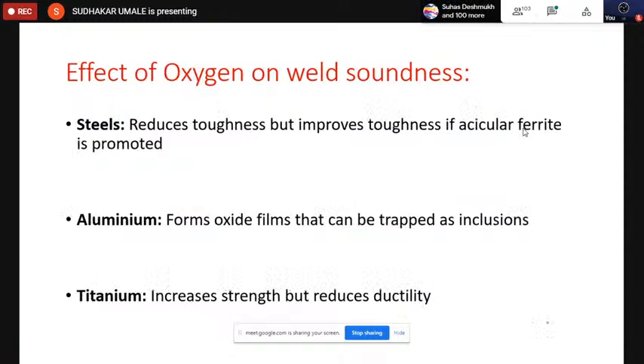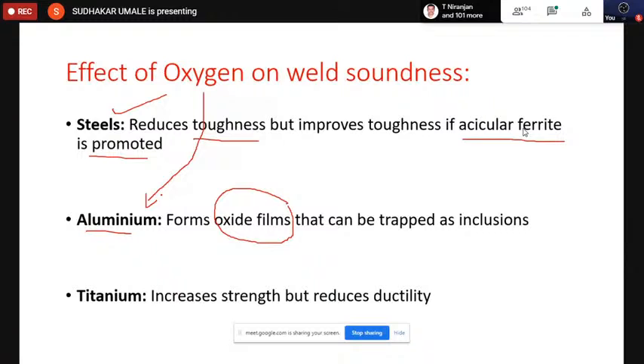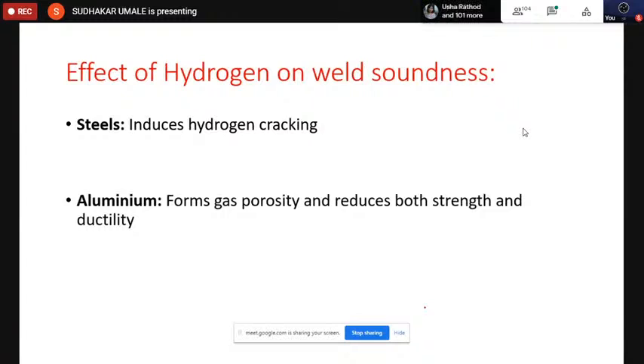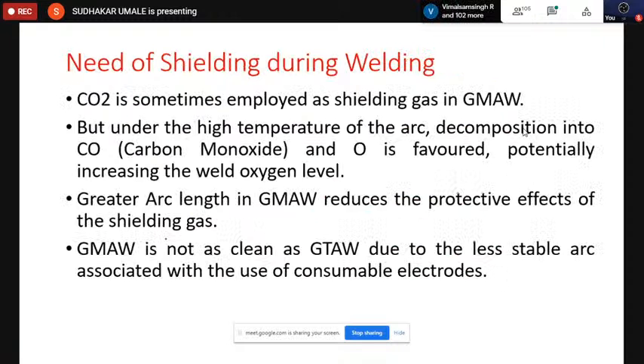Now, the effect of oxygen. When we are using steel, we have the same problems. Acicular ferrite is promoted, but it reduces the toughness. Aluminium forms oxide because of oxygen. Aluminium is very sensitive to oxygen, and these oxides, Al2O3, are considered inclusions, and this inclusion is very dangerous for welded joints. Titanium increases strength but reduces ductility. These are the problems. In the case of hydrogen, in steel it causes hydrogen cracking. In aluminium, it forms gas porosity and reduces both strength and ductility.